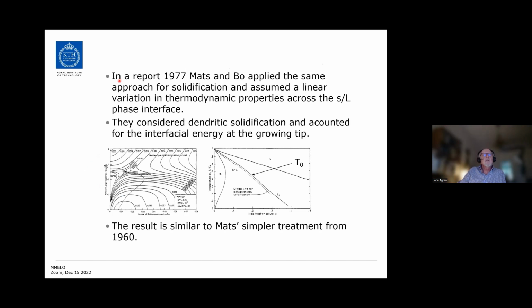And then a year later, Mats and Bo, they applied the same approach for solidification. And now they assume linear variation in thermodynamic properties across the solid-liquid phase interface. And they considered dendritic solidification and accounted for the interfacial energy at the growing tip. And this is the result they obtained. And you see, this is very similar to the much simpler treatment from 1960. So you have the curvature down here and velocity here. And then those curves are for different supersaturations.